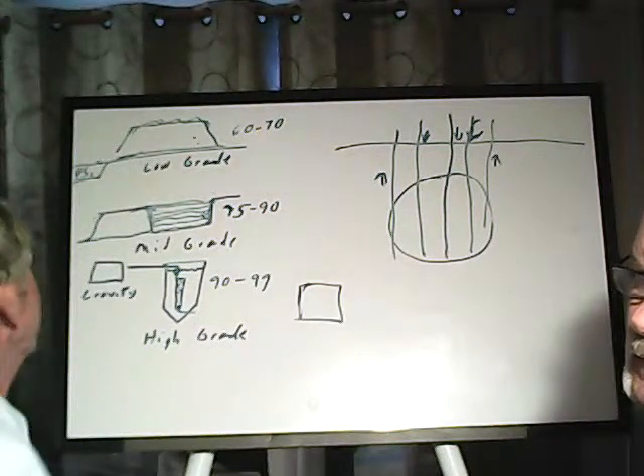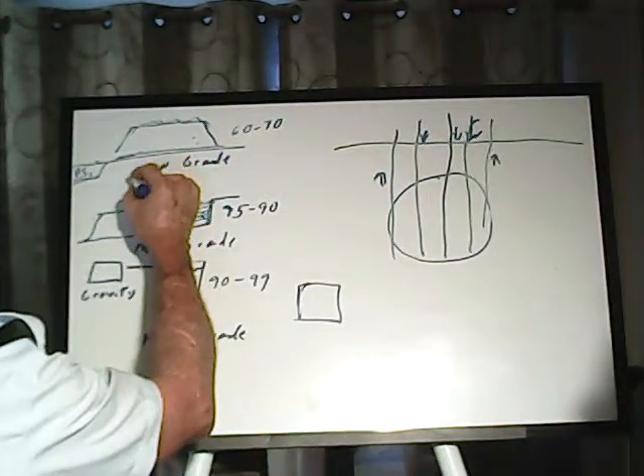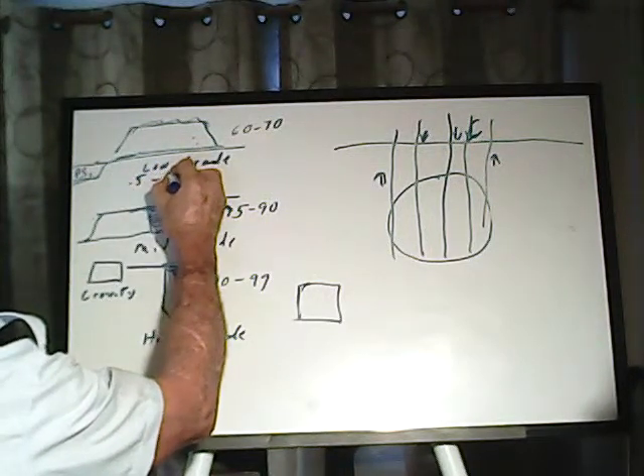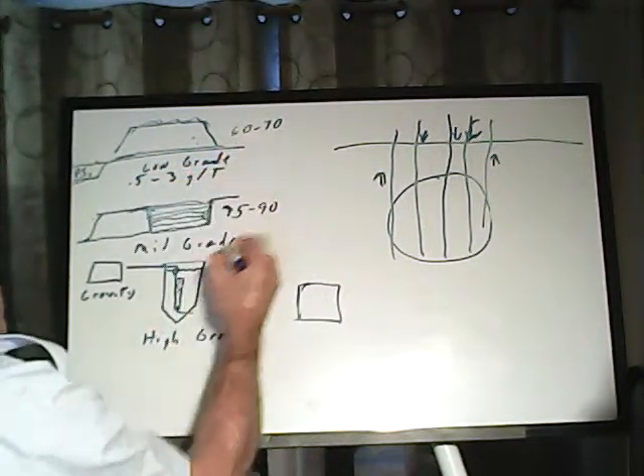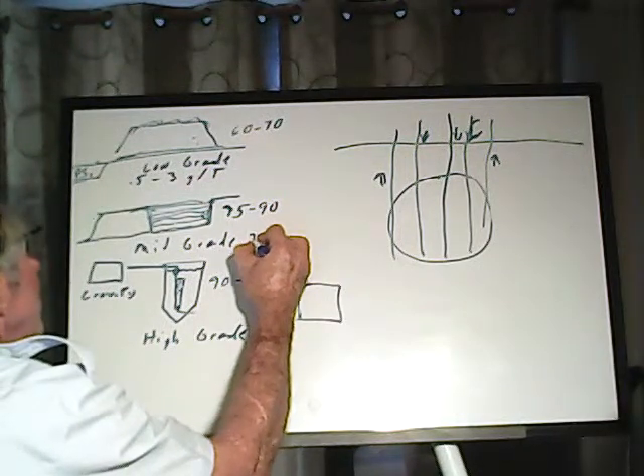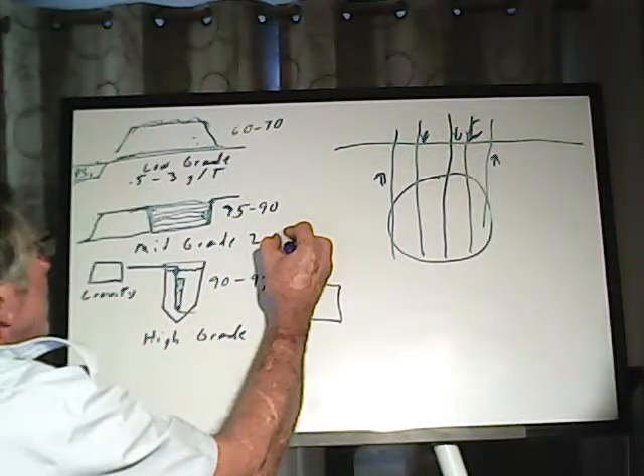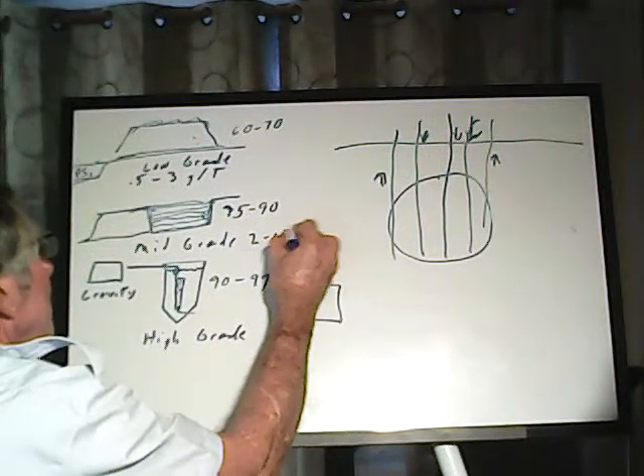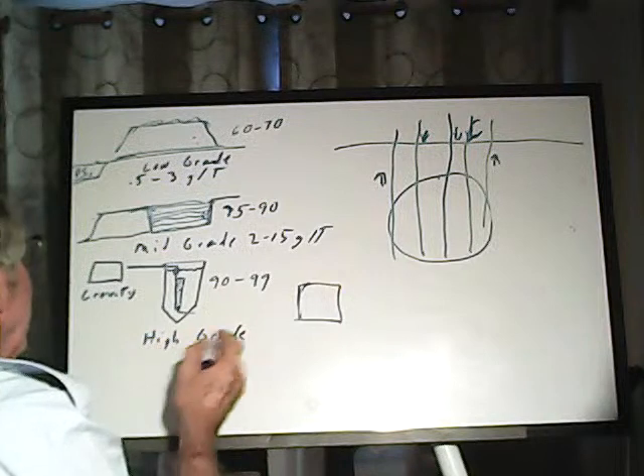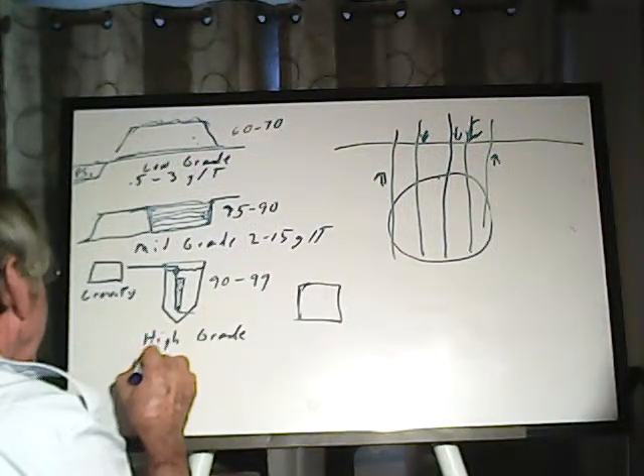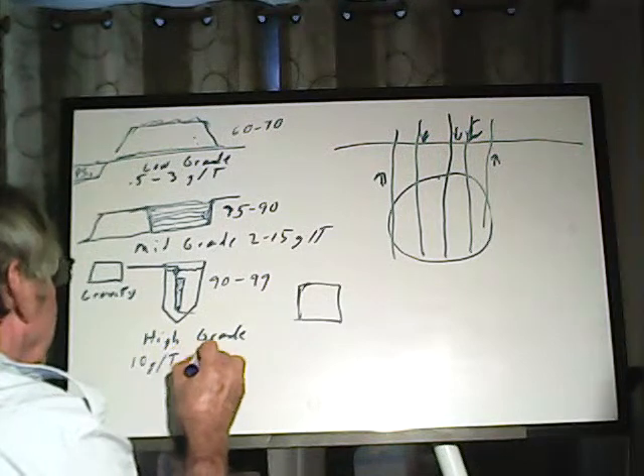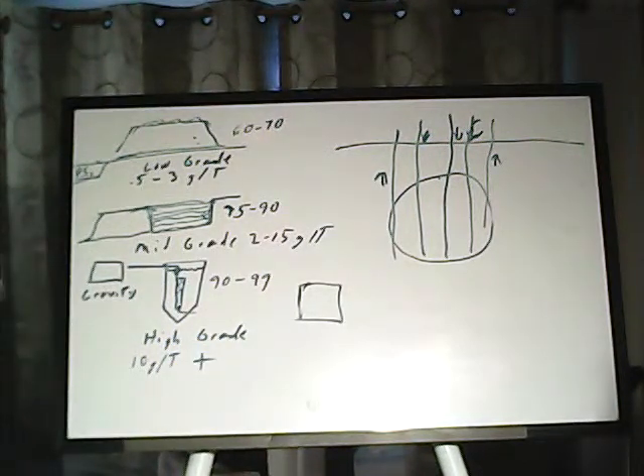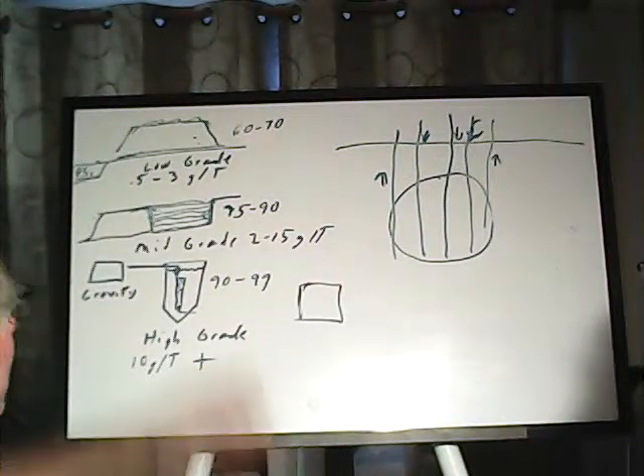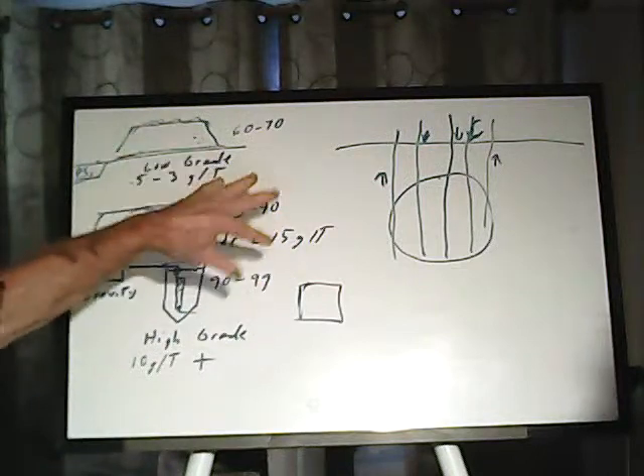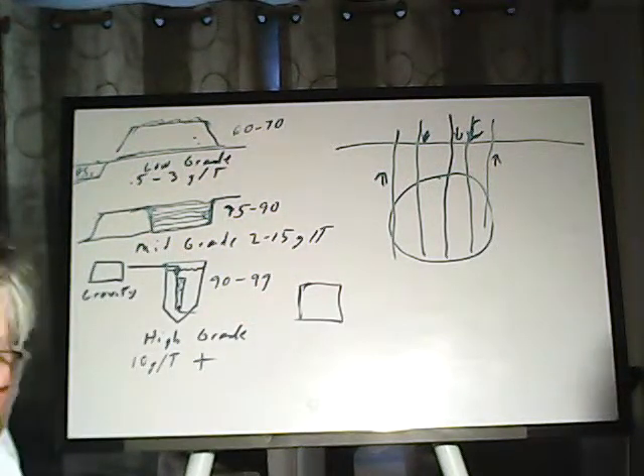Okay, Jason, what means low grade? How many grams per ton? Low grade is 0.5 to 3 grams per ton. Mid grade, 2 to 15 grams per ton. High grade, 10 grams per ton plus. Now, those are just rough numbers. It depends on a number of factors, like where your economic break-evens are and when you should go from one to the other. But those are rough industry standard numbers. It'll get you in the ballpark and give you an idea.